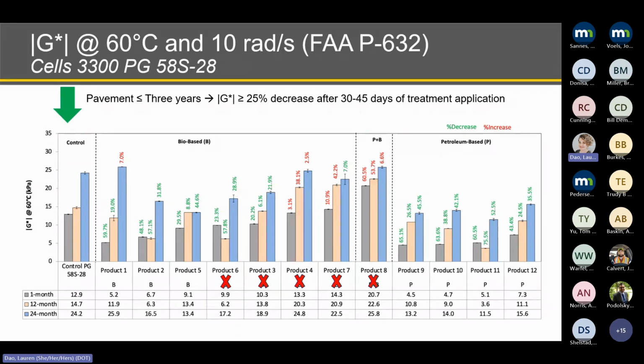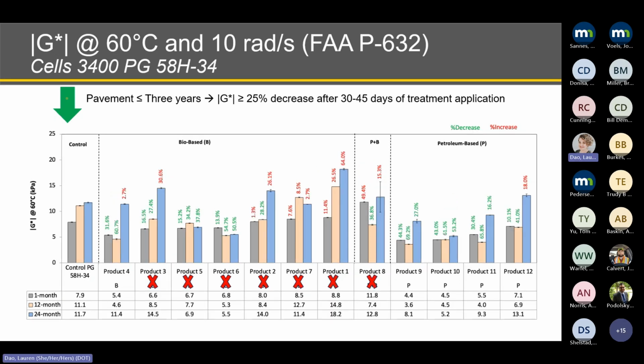However, for some of the products, like for example, product 6 and product 3, we saw that over time, they would pass that criteria of the P632 procedure, while, for example, product 7 and product 8 would not. Same evaluation was performed now for the polymeric asphalt surface with a PG binder 58H-34. On that specific treatment, as we saw from the previous data presented, these treatments did not reach their peak effectiveness after 1 month of application, but rather later on. So we would discriminate much more, or eliminate many more treatments, considering the polymeric asphalt surface, right, as we were considering the PG 58S-28.